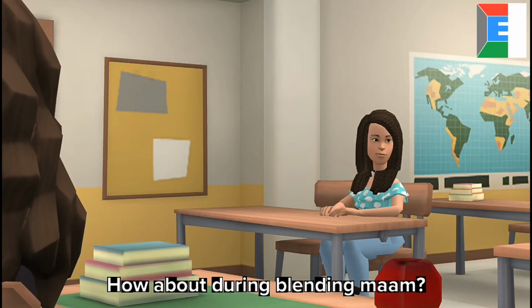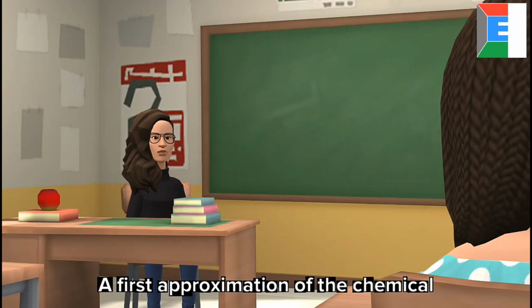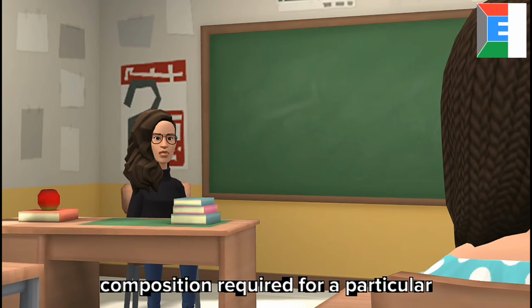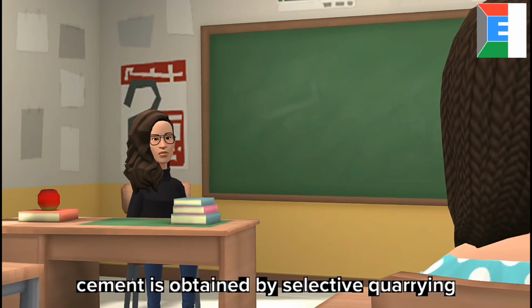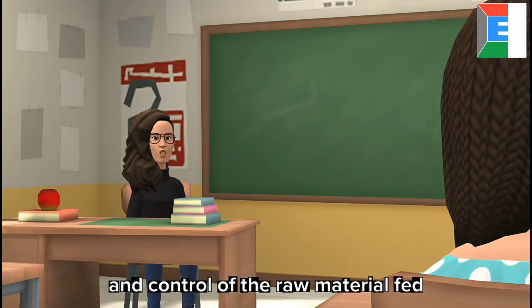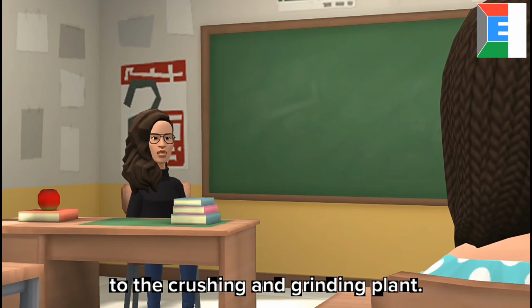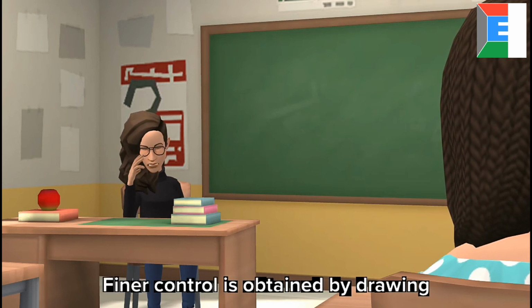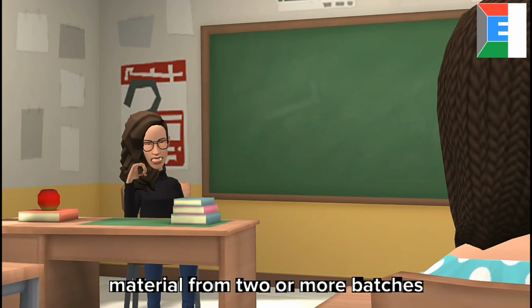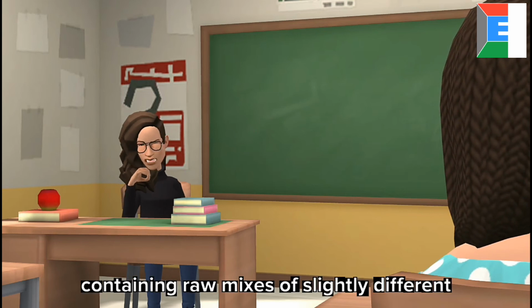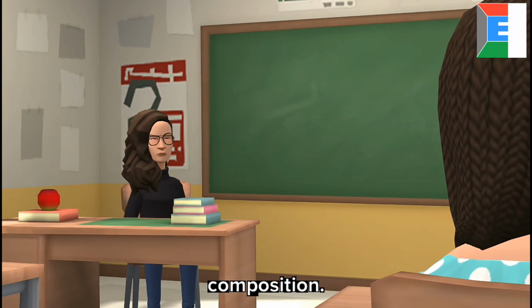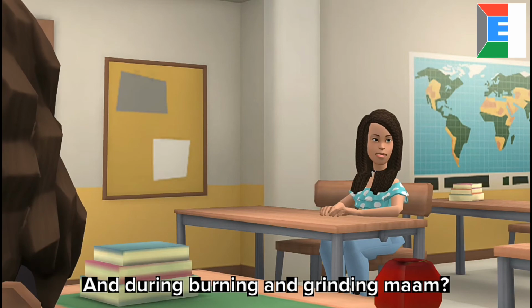How about during blending, ma'am? A first approximation of the chemical composition required for a particular cement is obtained by selective quarrying and control of the raw material fed to the crushing and grinding plant. Finer control is obtained by drawing material from 2 or more batches containing raw mixes of slightly different composition. And during burning and grinding, ma'am?